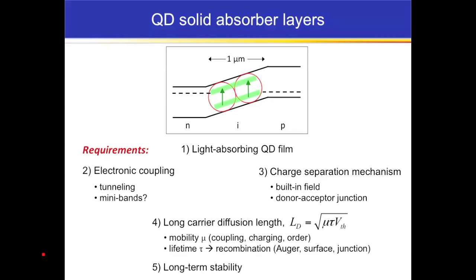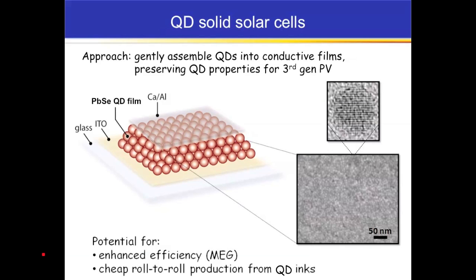Boosting the mobility, that means we need to couple the quantum dots very well together. We need to worry about things like charging energies that can obstruct charge transport, and we need to worry about disorder within the film. And the lifetime basically comes down in the case of quantum dots because of the very high surface area. We need to worry about surface recombination effects. And finally, we need to have long-term stability in order to have a practical kind of technology. So this is the game plan.